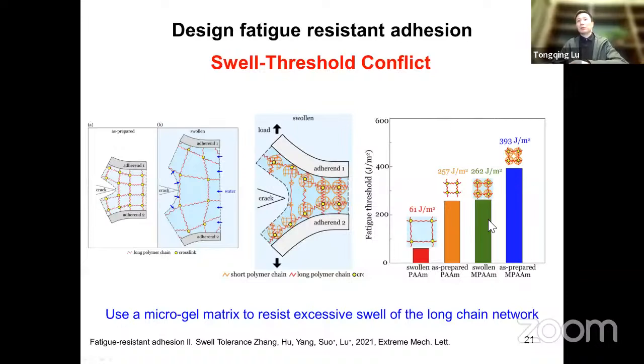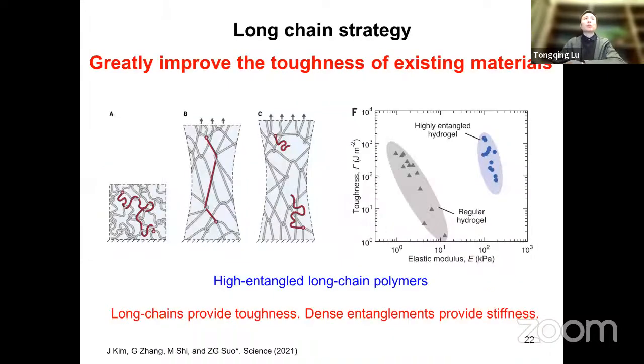So here's our experimental result. For example, if you use only as-prepared PAAm hydrogel as an interface, the fatigue threshold is about 200. But if you swell it, after swelling, the fatigue threshold will reduce to about 1/3. But if we use this microgel matrix reinforced hydrogel, we can see that even after the hydrogel was fully swollen, the fatigue threshold still remains at a high level. And this number actually is good for most biomedical applications. So this is another demonstration of this long chain strategy.